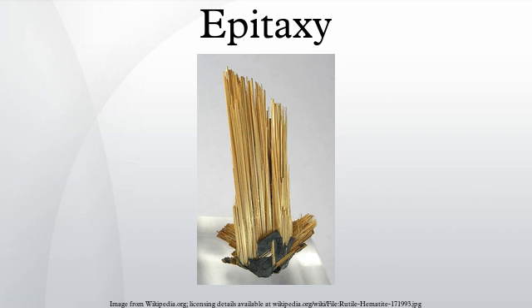Solid phase epitaxy is a transition between the amorphous and crystalline phases of a material. It is usually done by first depositing a film of amorphous material on a crystalline substrate, then heating the substrate to crystallize the film, with the single crystal substrate serving as a template for crystal growth. The annealing step used to re-crystallize or heal silicon layers amorphized during ion implantation is also considered a type of solid phase epitaxy. The impurity segregation and redistribution at the growing crystal-amorphous layer interface is used to incorporate low-solubility dopants in metals and silicon.